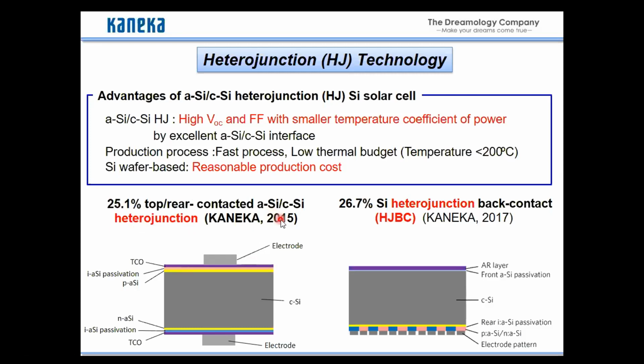The other one is back contact, where both polarity electrodes are integrated only at the back side. This is also passivated by amorphous silicon, and the passivation quality was a key issue to improve the efficiency. Of course, it has no electrodes at the front side, so there is no shading. So high current can be obtained. Normally in the case of top and rear contact, there's a trade-off between electrode resistivity and shading loss. But back contact can design the electrodes more freely, since we don't need to take care of shading at the front side.